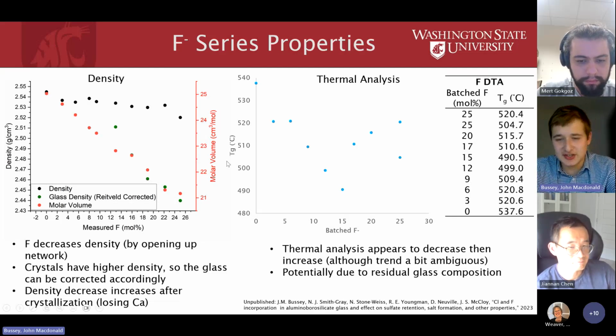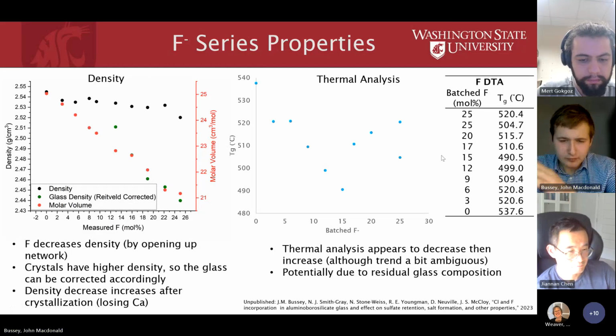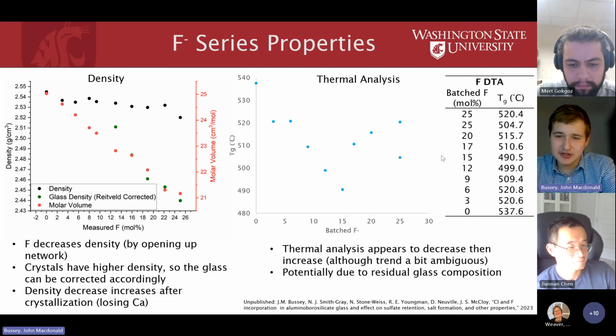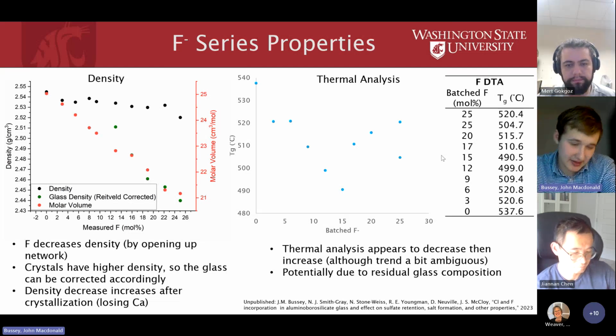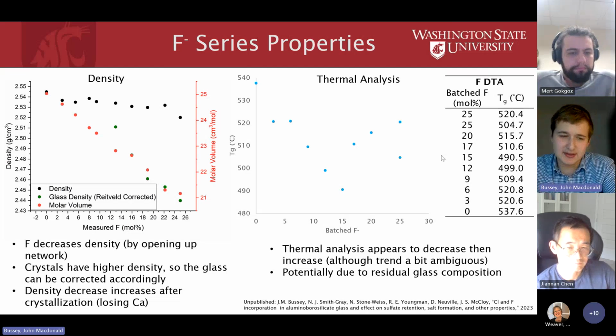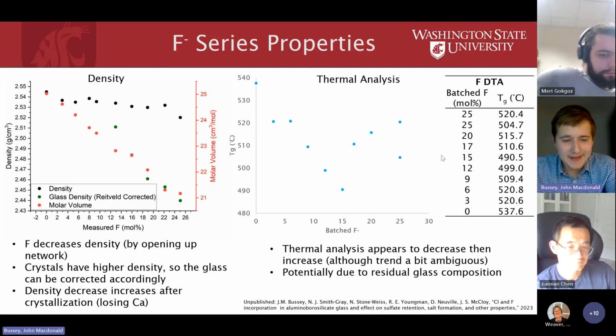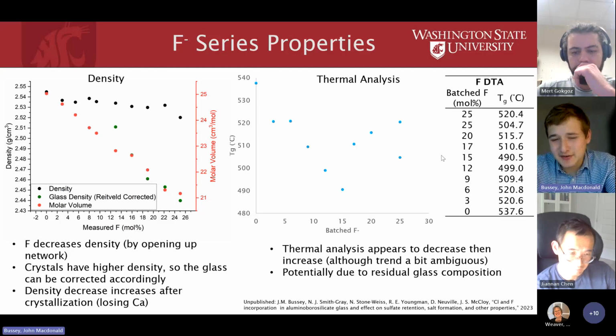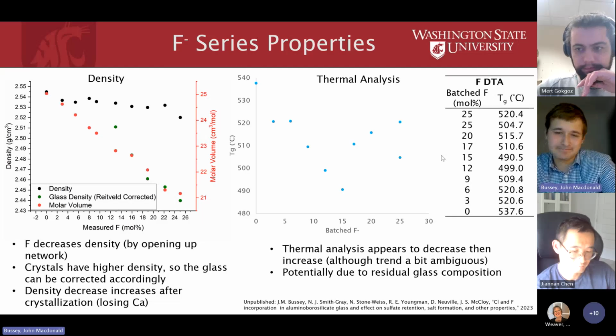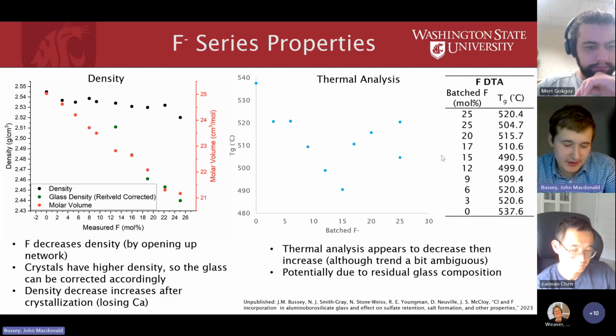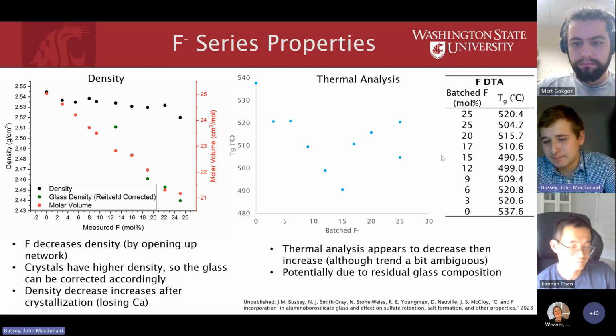Thermal analysis was much more complex. It's hard to see a trend really with this plot. However, the fluorine initially very much decreases the glass transition temperature, which again makes sense because it's opening up the network, it's causing depolymerization. And then what happens afterwards is a bit more ambiguous, if I can say that. But probably it's due to how the residual glass is changing once the fluorine leaves.